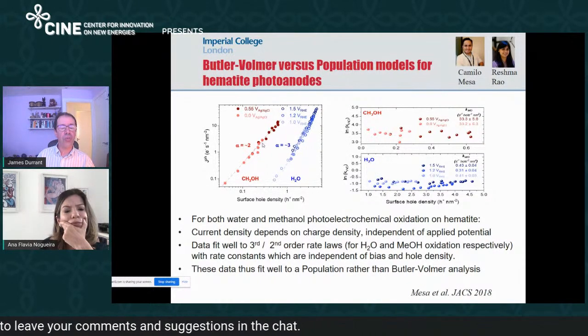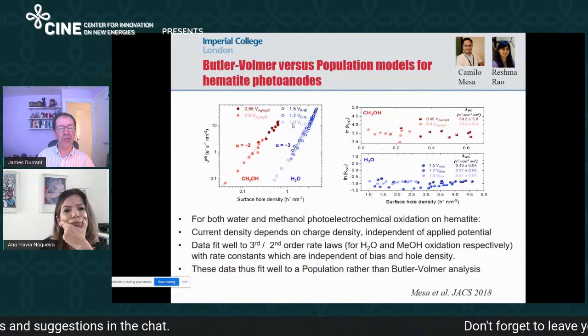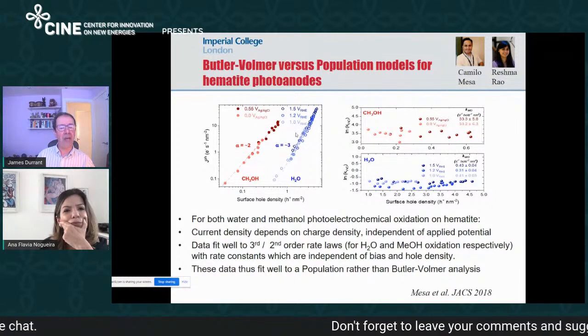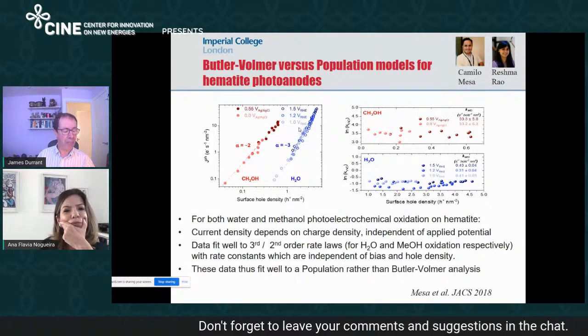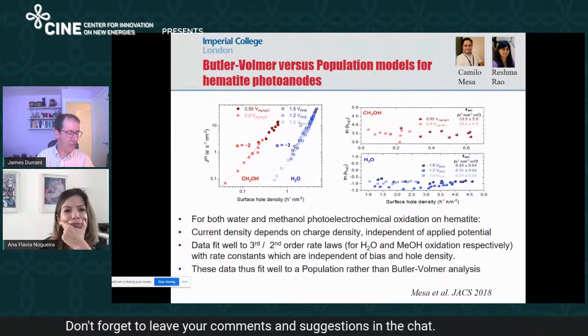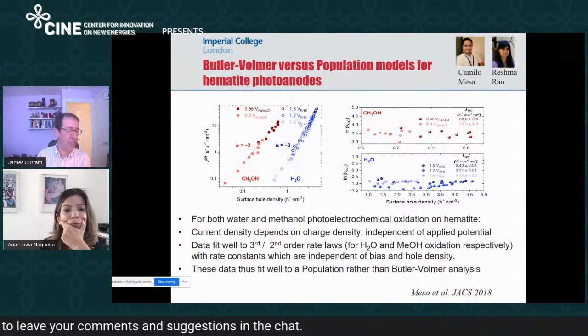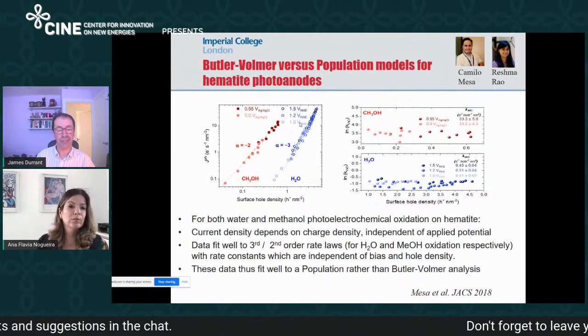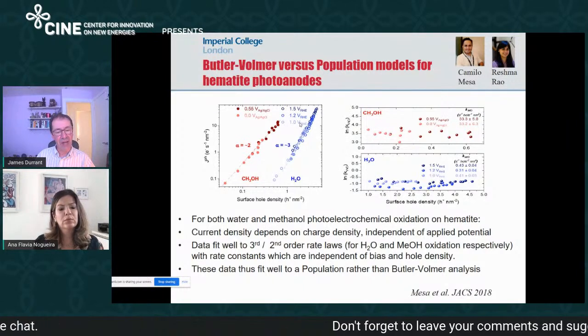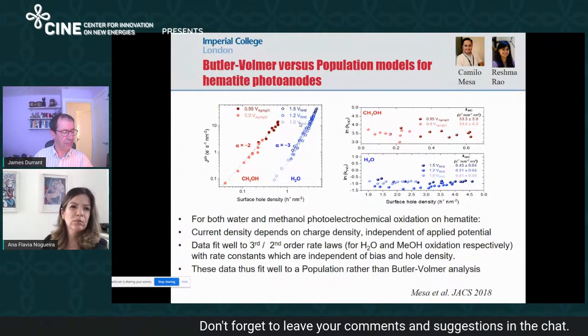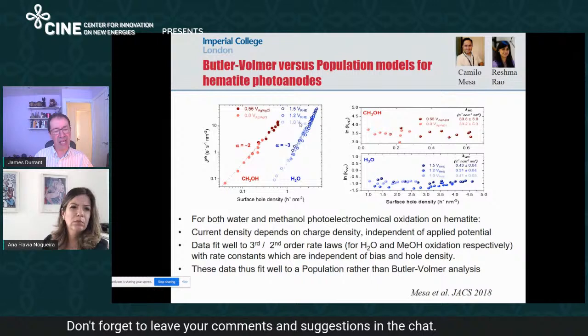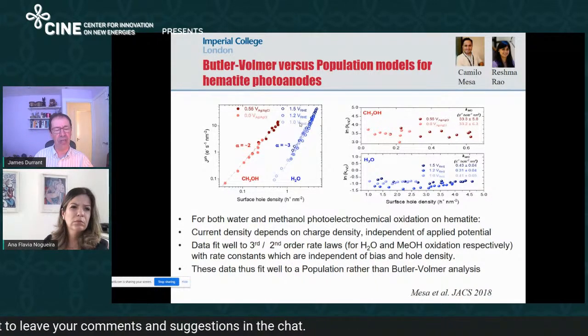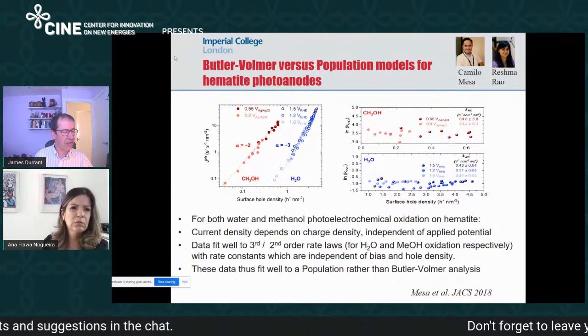And so what we are concluding is that whilst, of course, having more applied potential helps separate the charge, so you need fewer photons to generate a certain hole density at the surface, the potential itself doesn't change the catalysis. So the potential is changing the charge separation, but it's not changing the catalysis. Does that make sense? Yeah.